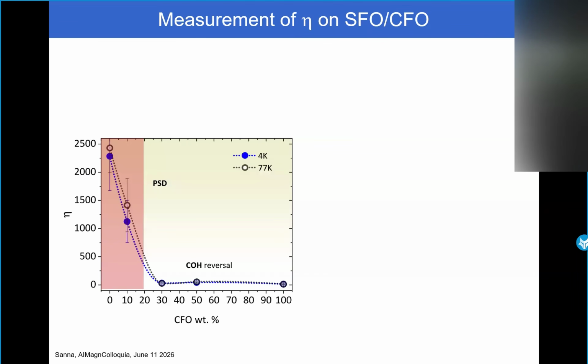And you can see what we observed. The enhancement factor, this amplification factor, which is very high for very soft materials and very low for hard materials, changes a lot when you introduce the CFO. Actually, I must say, also with, where is Pierre? Here. With Pierre, we were a bit confused at the beginning, Pierre, Davide, why is this so high?